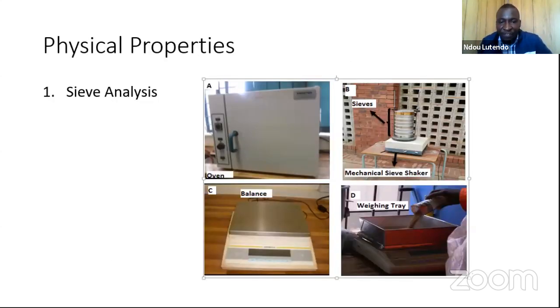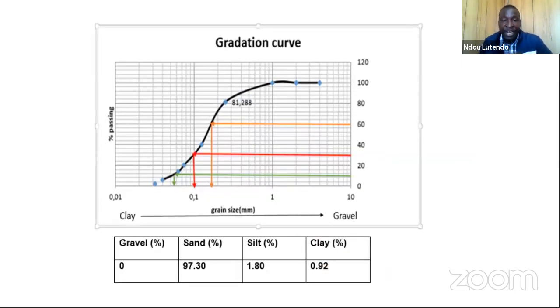Now the physical properties, starting with sieve analysis. This is how sieve analysis is used. You dry your material, put it under a mechanical sieve, shake it, and then weigh before and after. And this is the graph, the gradation curve. My material was actually composed of 97% sand.